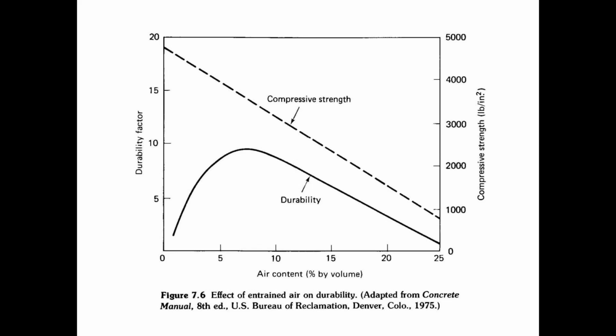But once we've got that water cement ratio dialed in and we're looking at our air entrainment, we also want to keep that on the low side of our target value because we can increase our durability and minimize the amount of compressive strength that's being lost. So as an example, if I know my durability is going to peak around 7%, then between 4% and 10% air content, I'm essentially going to have the same level of durability. But I'm going to have a much better compressive strength at 4% air than I'm going to have at 10% air. And so for that reason, I'm going to stay on the low side of that air content range.